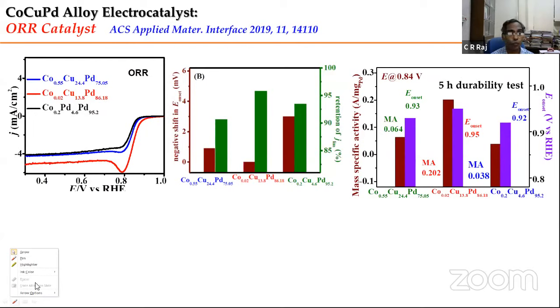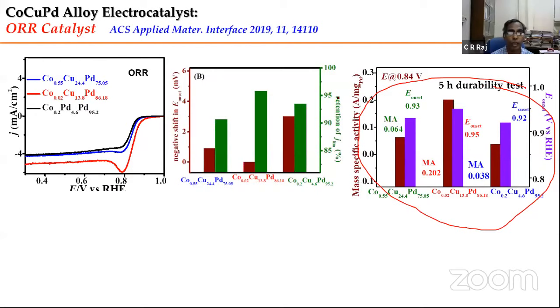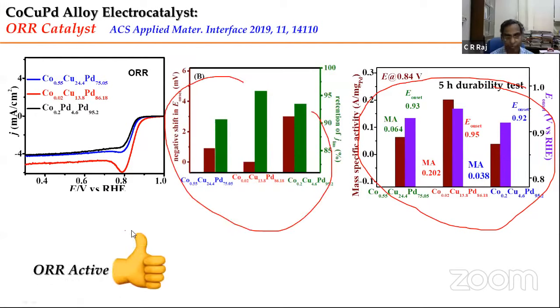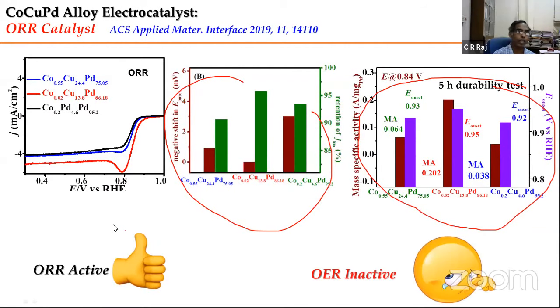You have a 5-hour durability. You check it, you have very good durability, activity is fantastic. But the problem is that it is ORR active, but it is not OER active. I cannot go and fabricate my Zinc Air Battery, right? Failure number one. I learned some lessons, but I could not achieve my target, because it's not an oxygen evolution catalyst. ORR is the oxygen reduction reaction. Here is the oxygen evolution reaction.